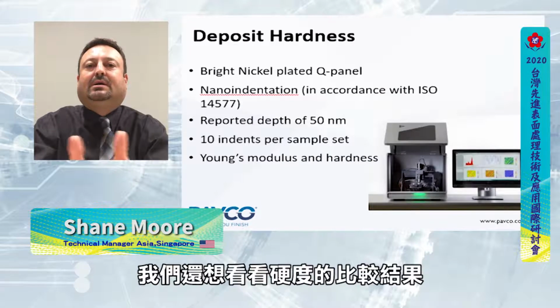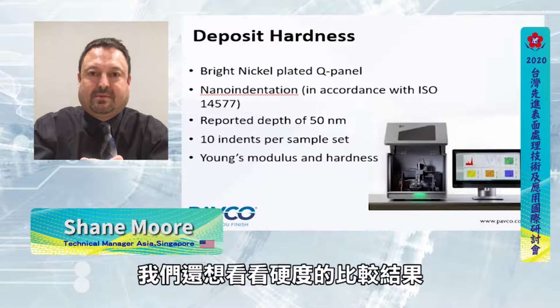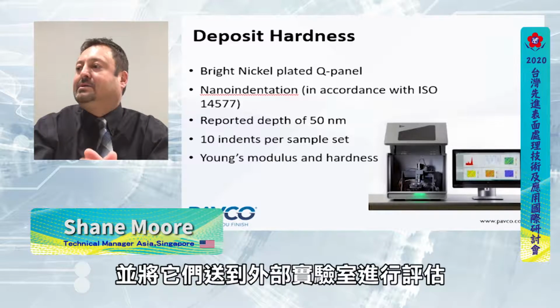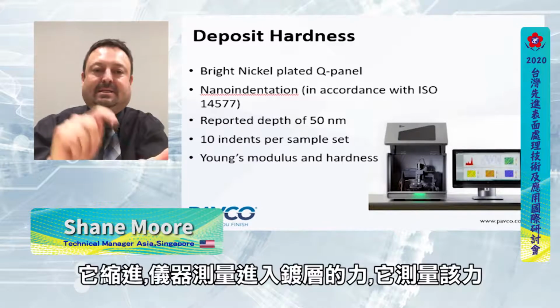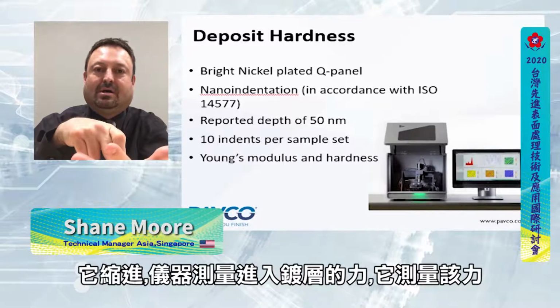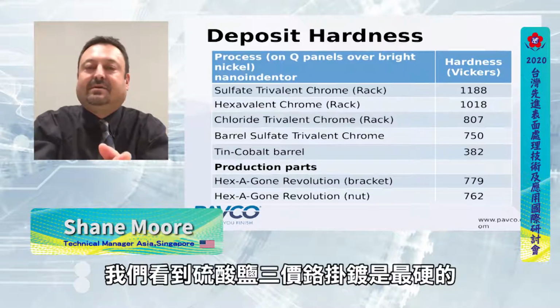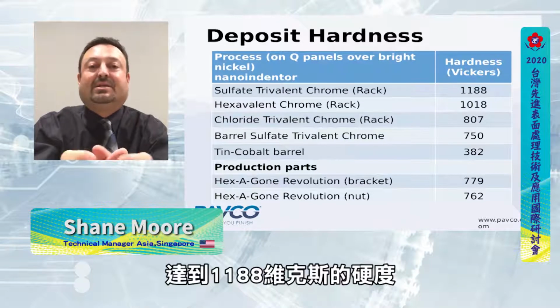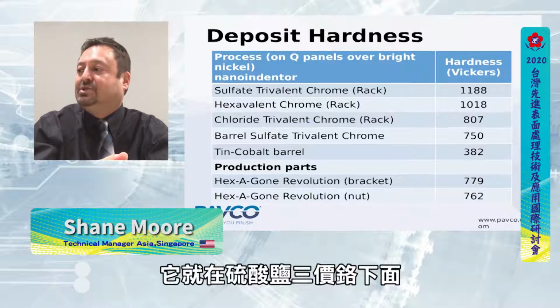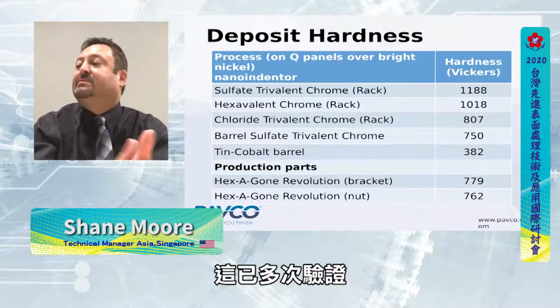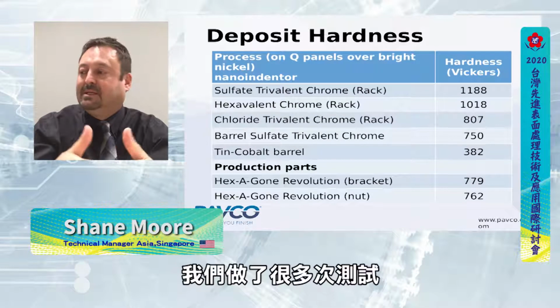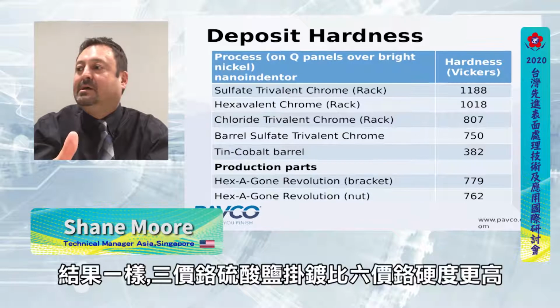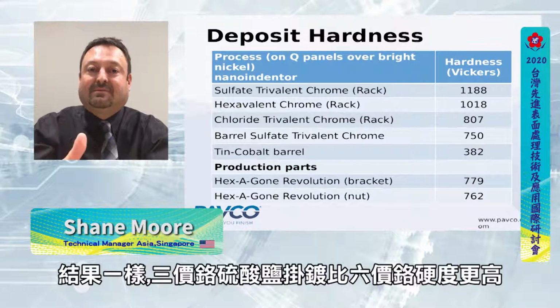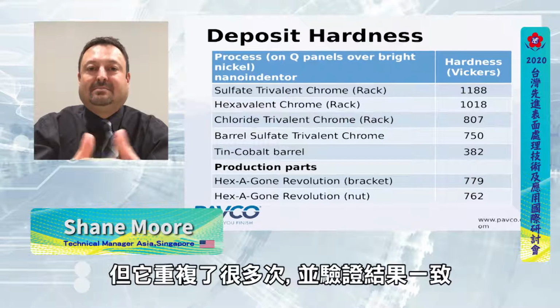Okay, and we also wanted to see how the hardness of the deposit compared. We plated more of these parts again, and we sent them to an outside lab to get evaluated. It is called a nano indentation. It basically indents and it measures the force, and what we saw was that the sulfate trivalent chromium rack application was actually the hardest. It came in at 1,188 Vickers. Next in line was the hexavalent chromium, and it was just under the sulfate trivalent chromium. And this has been verified many times. We've done this test many different times, and it always comes back that trivalent chromium sulfate based in a rack was actually harder than hexavalent chromium. Kind of surprising, but it was repeated many times and verified.